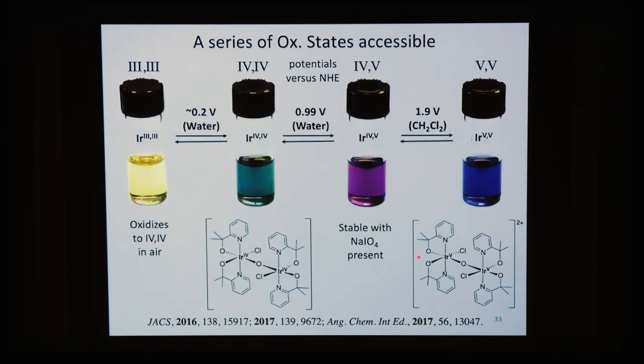And we can access a series of oxidation states. Reduction gives us the 3-3 form in which protonation takes place at the ligands. Oxidation gives us the 4-5. And further oxidation to the 5-5 is not possible in water because we start to break down the water. And so we have to do it in dichloromethane. And amazingly, the student was able to get crystals and get them tested for their structure. And they do indeed have the expected structure.